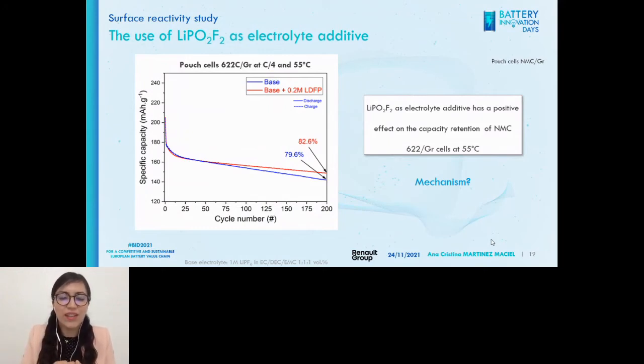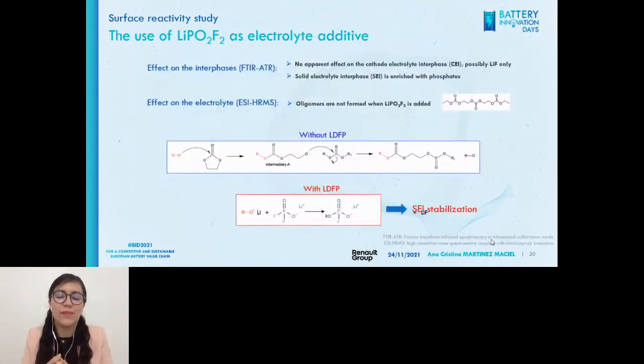That is how we performed several studies - one of the interfaces and another of the electrolyte. From the interfaces, we learned that there is no apparent effect on the cathode electrolyte interface. Right now we are hearing a lot about cathode electrolyte interfaces, but in our case there was no effect, possibly only LiF.